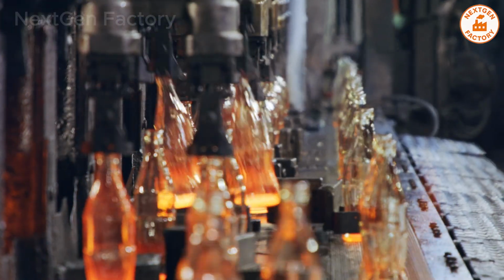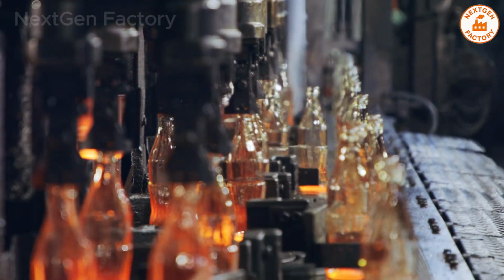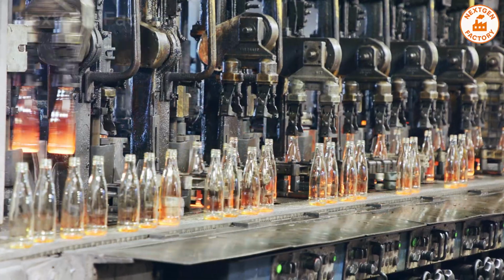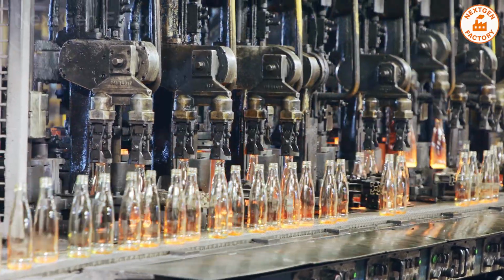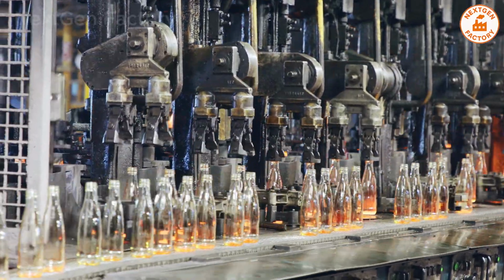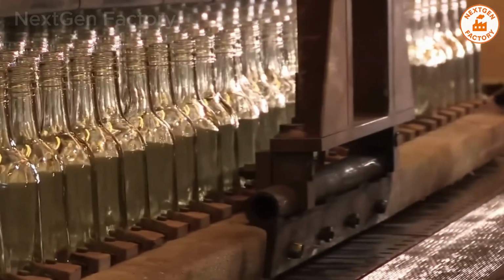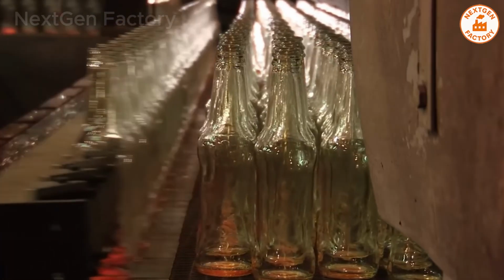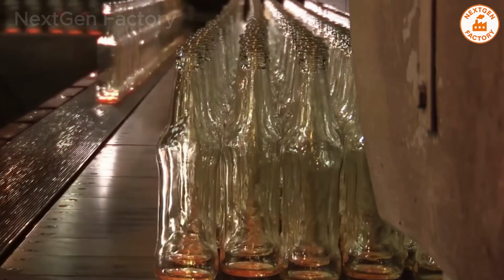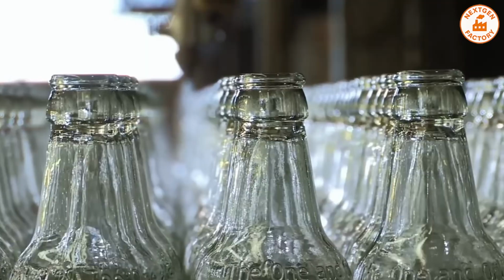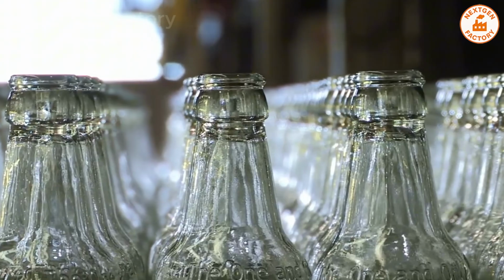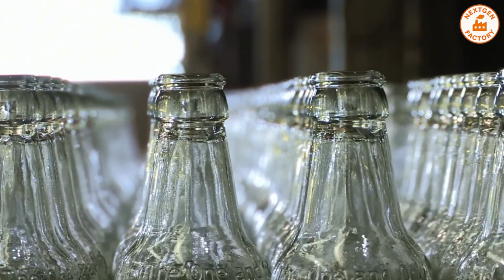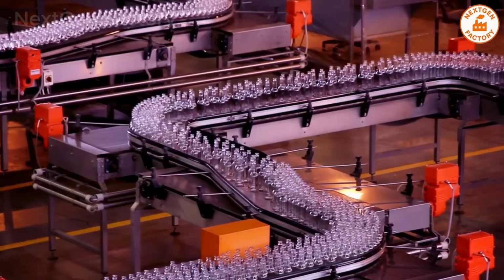Freshly formed bottles are extremely fragile because of internal stress created during shaping. To relieve this stress, they move through a long tunnel called an annealing lehr. Over several minutes, the temperature gradually decreases from hundreds of degrees Celsius down to ambient temperature. Without annealing, the glass would crack or explode under the slightest pressure. Properly annealed glass is stronger, safer, and far more reliable.